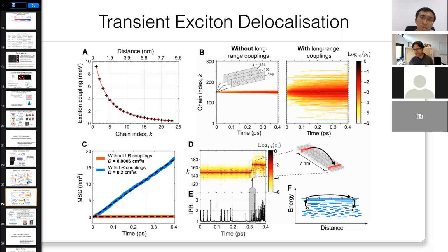Yeah, so this is again a beautiful aspect of the organics, something very peculiar to molecular systems. The reason is that the organic molecules are changing conformation, right? If the system was static, if you had no structural movement, if you had no vibration modes, then the fully delocalized state would be the lowest energy state. That's what you'd expect. It's the particle in the box. If I make my box any smaller, that should increase the energy. It's what you see in inorganics, semiconductor quantum dots, exactly that. But over here, because the molecule can change its shape, the delocalized states can be lower because the molecule is essentially changing shape to lower the energy of that state further. So those states can be lower in energy because the system is dynamically changing its state.